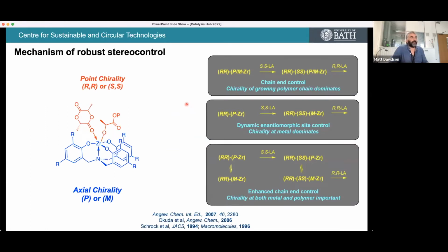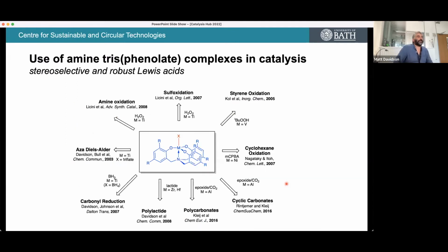We've done a lot of work on the mechanism. I don't really want to go into that in any detail at all. But this is the catalytically active species with a growing polymer chain here, and you can see that the lactide monomer coordinates to the zirconium center, which has the growing polymer chain on it, and then that ring opens and inserts to propagate the polymerization. The stereo control mechanism is interesting, but not really relevant to what we're talking about today. It turns out it's an enhanced chain end control mechanism.